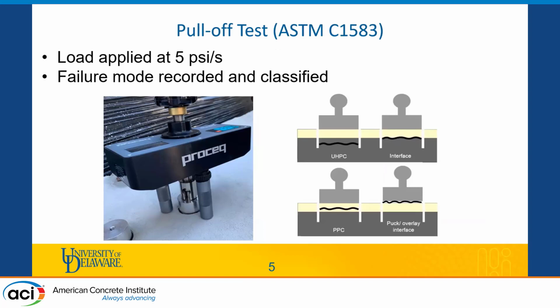Since we are measuring bond performance, we can evaluate our bond performance in terms of bond strength and failure mode. When conducting this test, 4 failure modes are possible. The first one is failure in the UHPC. You can also have failure in the PPC. You can have failure at the interface of UHPC to PPC, and you can have failure of the metallic puck.